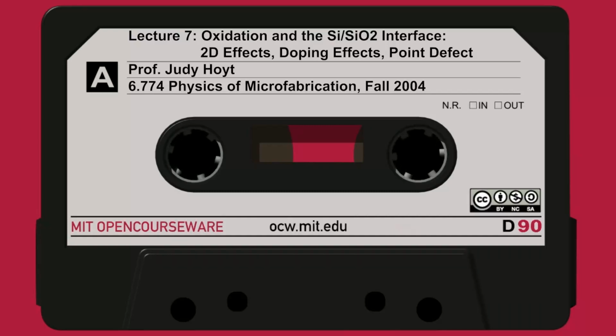But look at the top surface of this oxide here. Remember, when it first starts out, it's relatively flat. This top surface has to stretch in order to maintain this shape by as much as 15 to 20%. So the oxide is itself having to stretch and deform, and all that involves doing work and stress buildup.